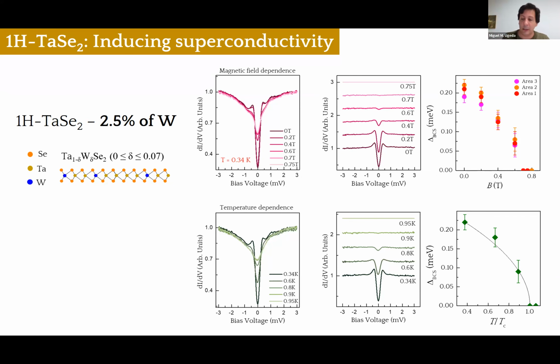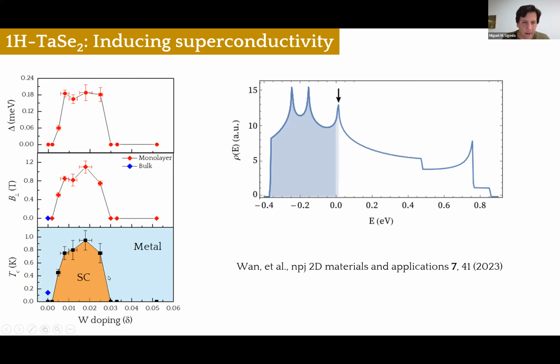So if we do that for different concentrations, we can end up building the phase diagram for this material, where we see a superconducting dome that spans from close to 0 up to 3% of tungsten doping. This is a dome with a maximal critical temperature of about 1 Kelvin, right? And this dome reflects the shape of the density of states as we go from one side to the other side of the Van Hove singularity, right? Okay, but unless you do this trick, the system is metallic, is not magnetic, and it's not superconducting. So this is the substrate that we have.